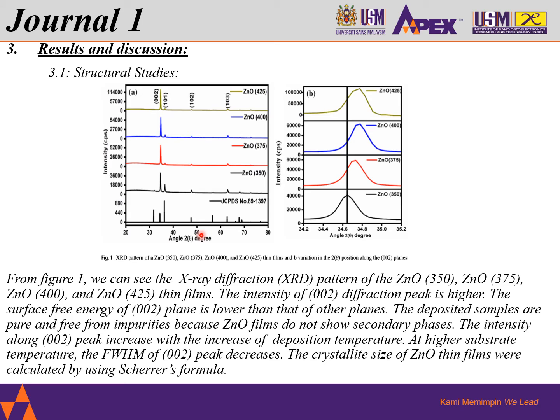The intensity of the 002 peak increases with the increase of deposition temperature. We can see here that while the temperature increases, the intensity also increases. At higher substrate temperature, the FWHM of the 002 peak decreases. The crystallite size of the zinc oxide thin films was calculated by using the Scherrer formula.